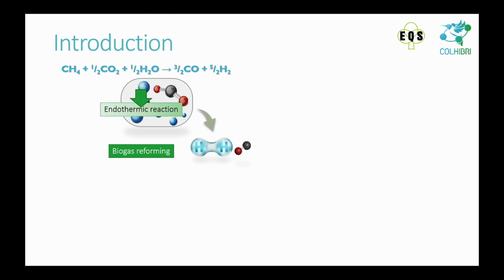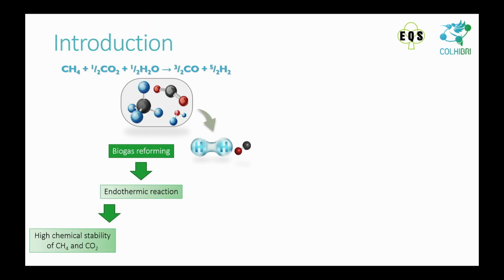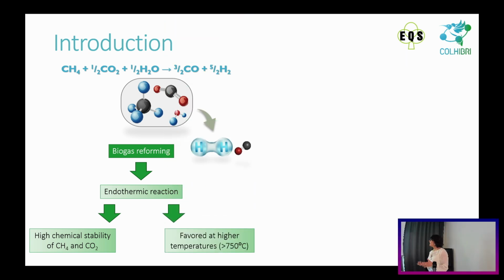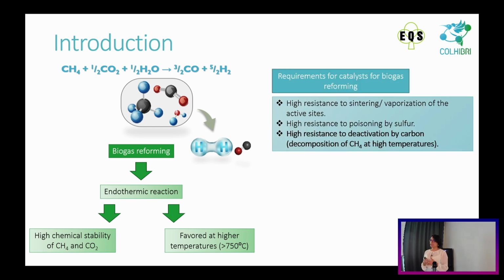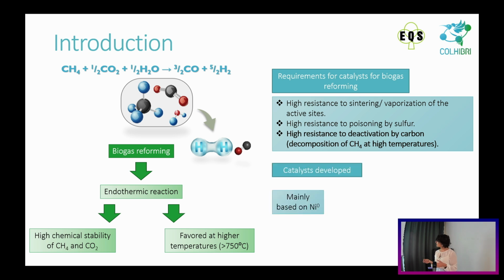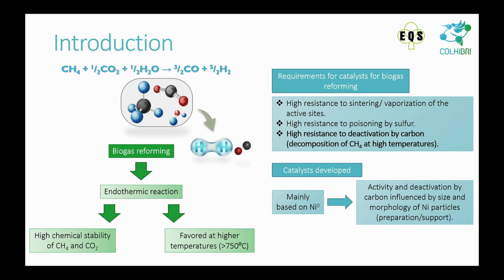So, biogas reforming is an endothermic reaction due to the high chemical stability of methane and CO2, and therefore it's favored at higher temperatures, which are above 750 degrees. For a catalyst to be able to do the biogas reforming, it needs to have high resistance to sintering and vaporization of the active sites, to poisoning, and to the deactivation by carbon because of the decomposition of methane at higher temperatures. The catalysts developed in the literature are mainly based on nickel, and the activity and the deactivation is influenced by the size and morphology of the particles, nickel particle size. So far, this reaction has not been implemented at industrial scale.